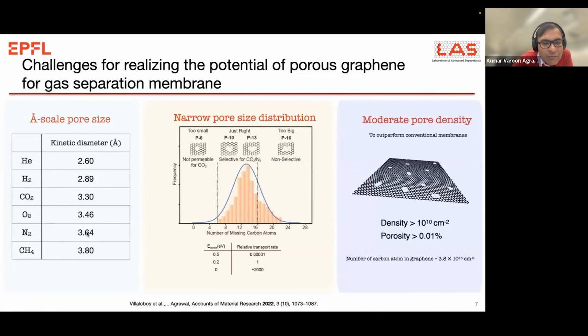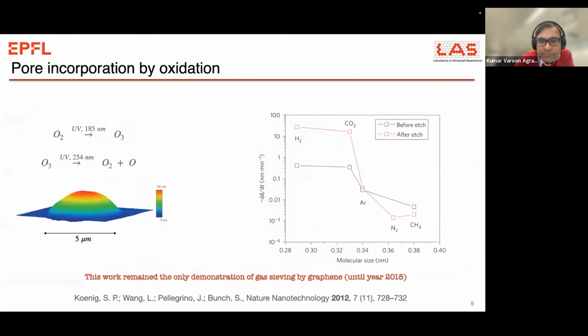Because if you have a bigger pore, it will allow nitrogen to go through. With a bigger pore there is no barrier, as I mentioned in the previous slide, so the molecules go really fast. And so one big pore will destroy the selectivity that you get from about 2,000 pores. So that's a big challenge. We have to be very specific, making a tight control on the pore size distribution. And the second is that we have to not just make one pore, but an ensemble of pores, so we have to have a certain pore density. The process that we use has to be very uniform and easily applicable.